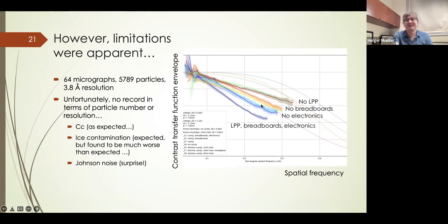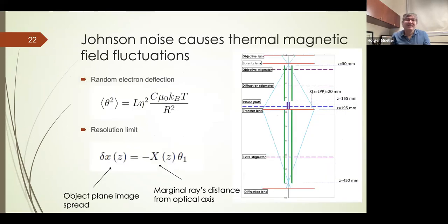So here on the right, you see our initial measurements, they were refined later, of the contrast transfer function envelope as a function of spatial frequencies. You see the dotted lines are theory curves, and you see the laser phase plate as installed performed much worse than theory. So what are we supposed to do? Well, it turned out after a lot of painful guesswork that Johnson noise was responsible for that.